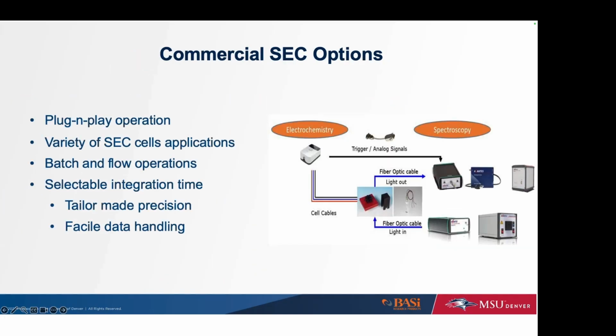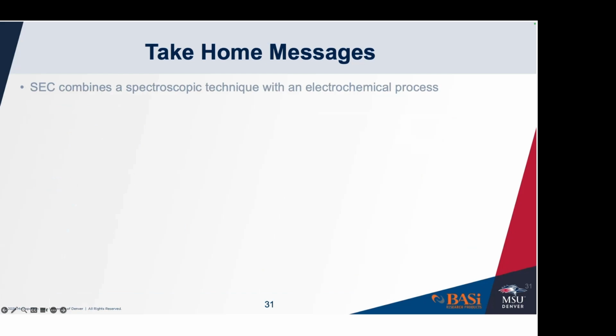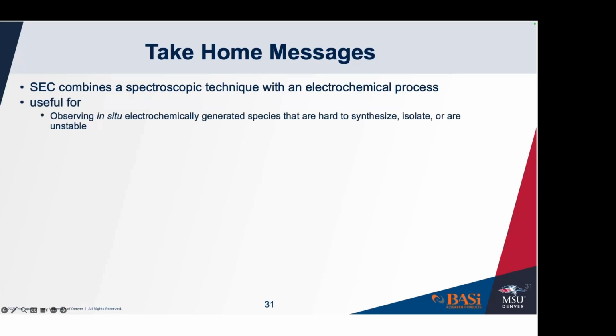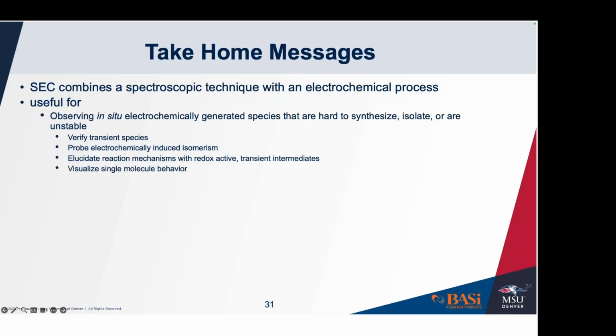All right, so the take home messages: spectroelectrochemistry is a combined technique that combines spectroscopy with an electrochemical process. It's useful for observing in situ electrochemically generated species that are hard to isolate, synthesize, or are unstable. We can verify transient species with spectroelectrochemistry. We can probe electrochemically induced isomerization. We can elucidate reaction mechanisms. We can visualize single molecule behavior, and we can do so much more. Your imagination is kind of the limit here.